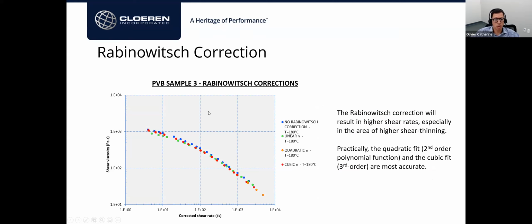We have data that we measured with our system, and in blue is the data for the shear rate, which would not be corrected. So no Rabinowitsch correction is shown there. Then in green, we have the linear correction of the Rabinowitsch, so basically a degree 1 polynomial function. And then in red and orange, we have quadratic and cubic, so a degree 2 and 3 polynomial function, which I think gives the best correction in the end. As I was explaining on the graph of the velocity profile, using a correction ends up shifting the data to higher shear rates. And that's what you see here.